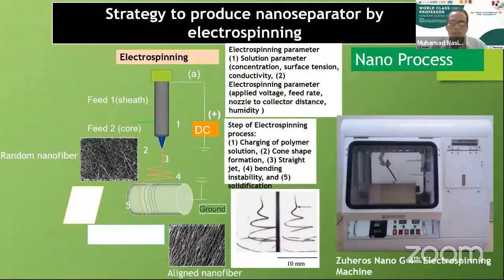Okay, this is the process or method to make a separator by electrospinning. There are electrospinning parameters. First is solution parameters, for example the concentration of polymer, surface tension of polymer, and conductivity of polymer. And second is electrospinning parameters, for example applied voltage, feed rate, nozzle to collector distance, and humidity. These are the steps to make a separator by electrospinning, because we use high voltage: first is charging of the polymer solution, cone formation, straight jet, bending instability, and solidification of the polymer. This is an example of the electrospinning machine we developed to make a separator.